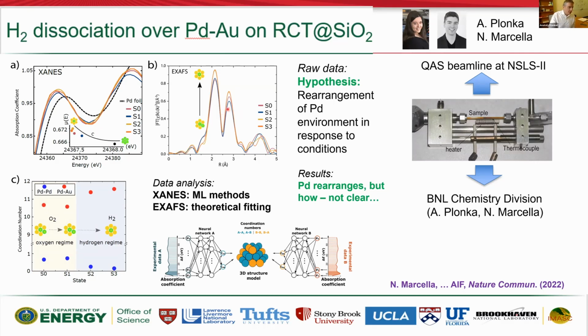And not only more neighbors, more gold neighbors, because you would not see palladium bonds in 8% palladium, very dilute. So that's qualitatively consistent with the explanation for restructuring, but we wanted to have it quantitative. And so we did full XAFS fitting, and we found that the uncertainties in the best fit parameters were quite large, and so the results really overlap within the uncertainties, and it's not nice. But when we performed this machine learning analysis of the XANES data, which is shown on the top left, which clearly shows a very interesting and very easy to understand trend, then we obtained much better and much more systematic answers. And they were consistent with XAFS, but with much smaller uncertainties.